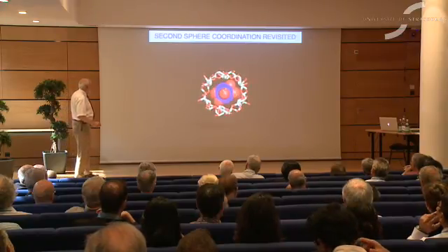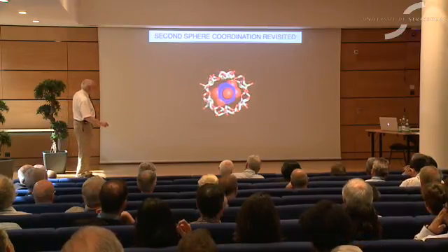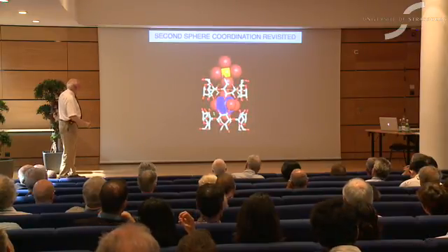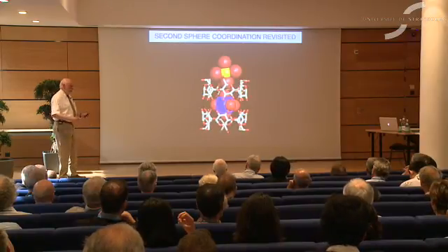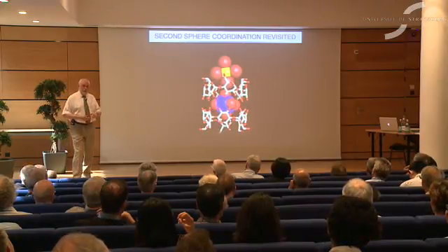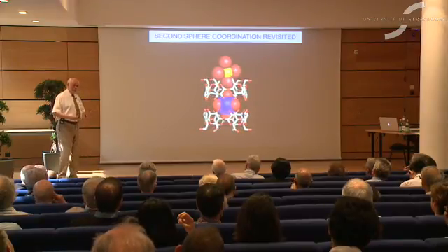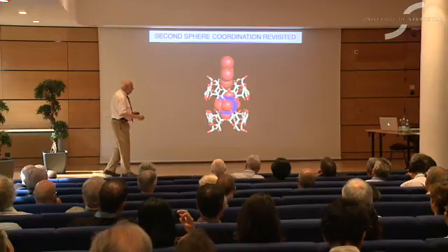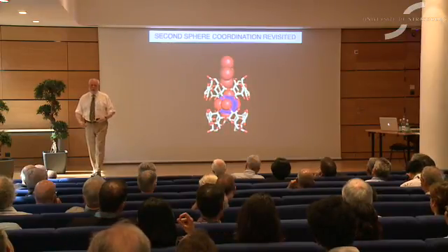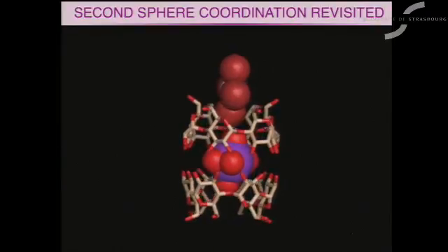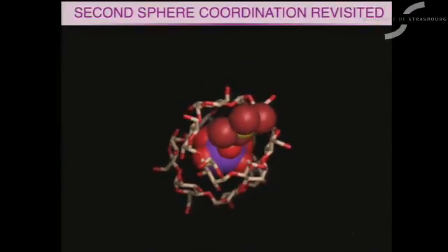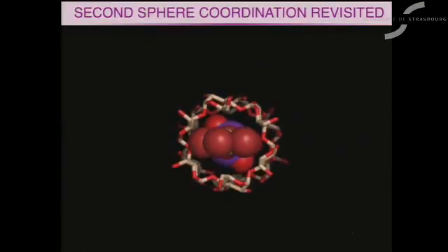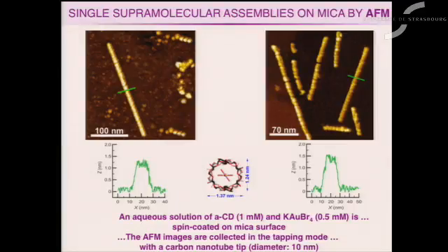Now we're looking at the water, where it'll be involved in O-H···O interactions with the cyclodextrin. And then you have interactions across here that are hydrogen bonded. And of course, all of this is probably dictated by some hydrophobicity. And don't forget the electrostatic charge, the plus and the minus that are being matched up here. So you bring together everything, and this is really a hand-in-the-glove fit. We don't get anything that really matches it. It's absolutely specific for the potassium tetrabromoaurate.